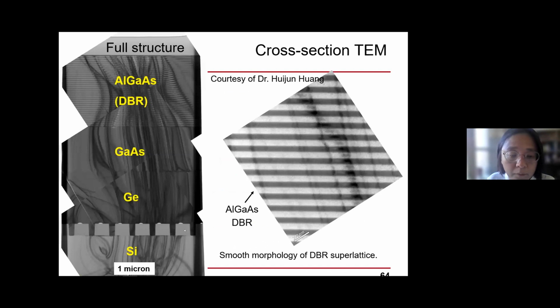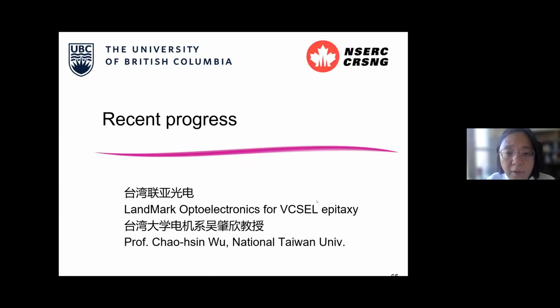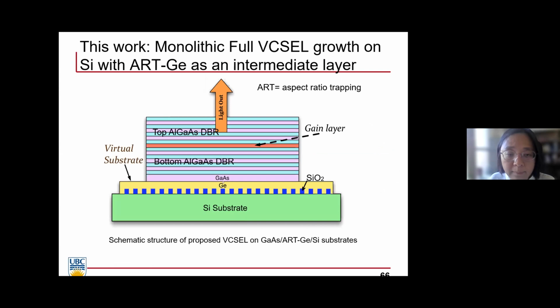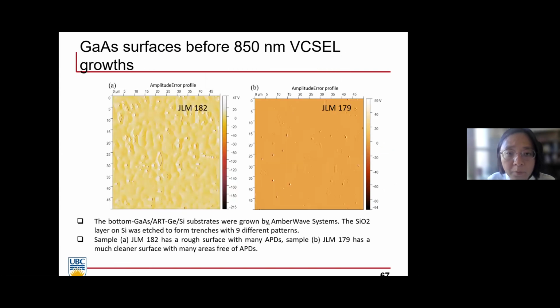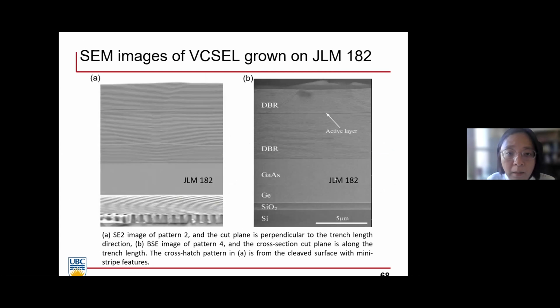performance. And if you look at this TEM, silicon, germanium, gallium arsenide, and aluminum gallium arsenide DBRs, really smooth and nice growth. And in recent progress, we actually already tried to grow the full VCSEL epi on silicon substrate. This goes from silicon, germanium, gallium arsenide, and full VCSEL. Of course, anti-phase domain is the main problem. Before growth, there are some anti-phase domains already. But after growth, it really depends on the regions. We can have pretty smooth local structures, and this one shows pretty smooth local structures, and you see the periodicity has been very reasonable.